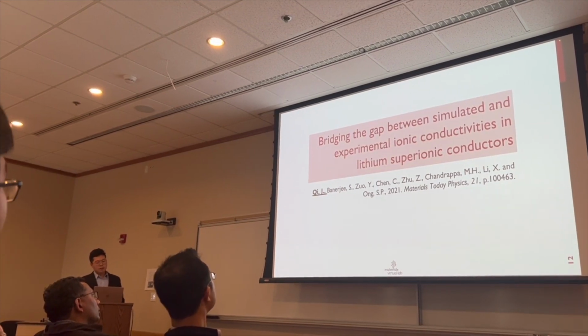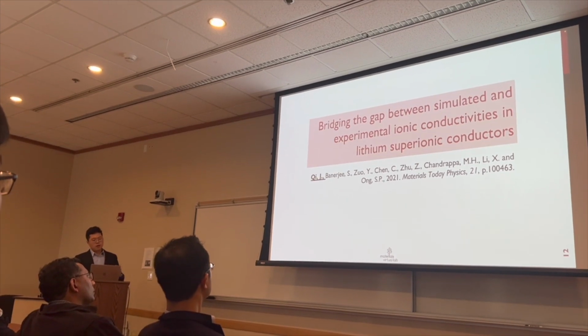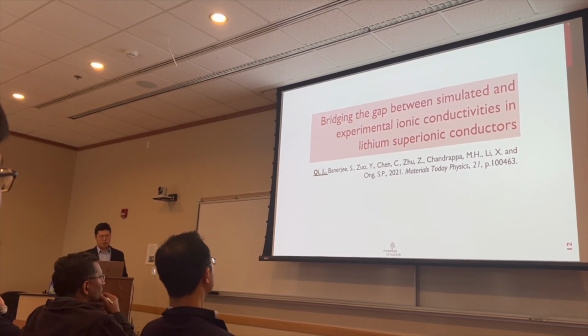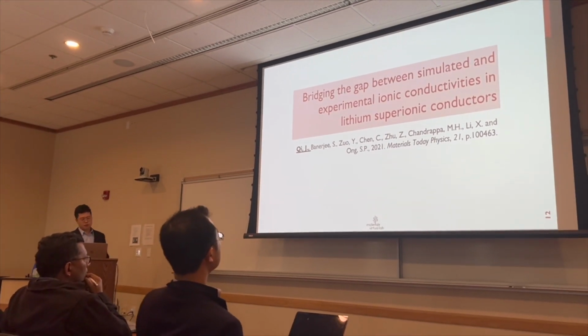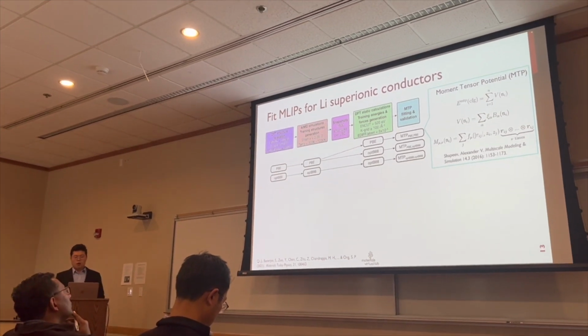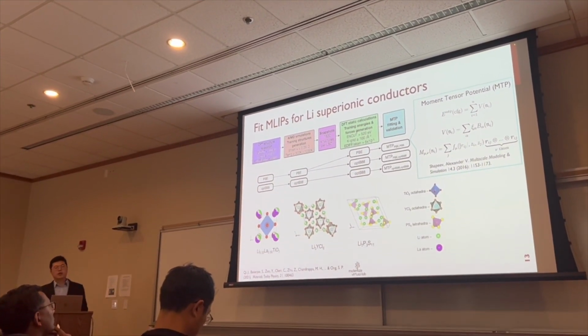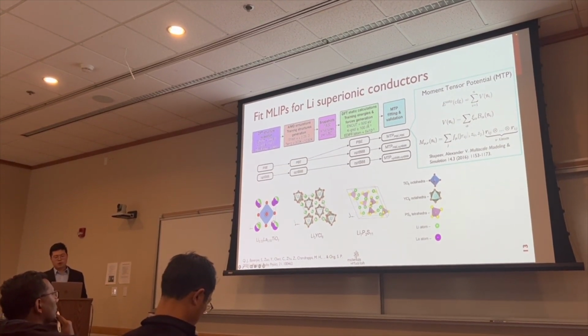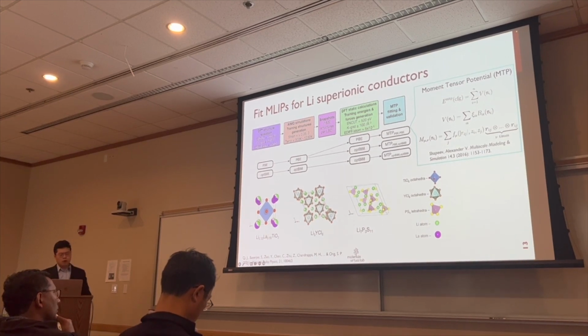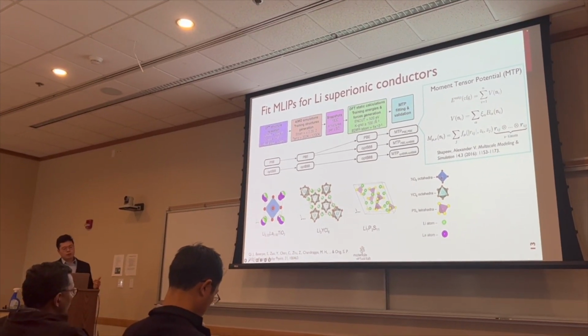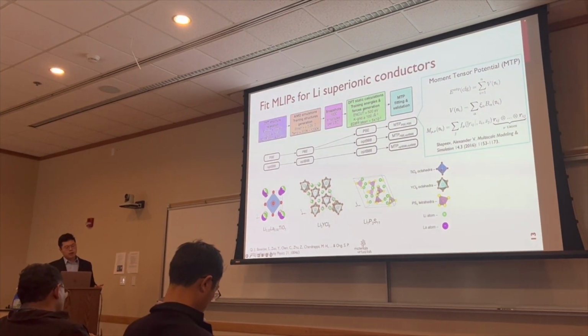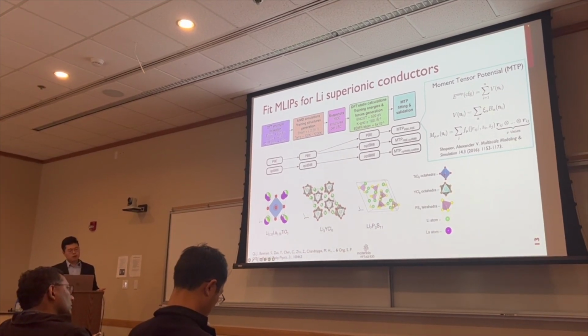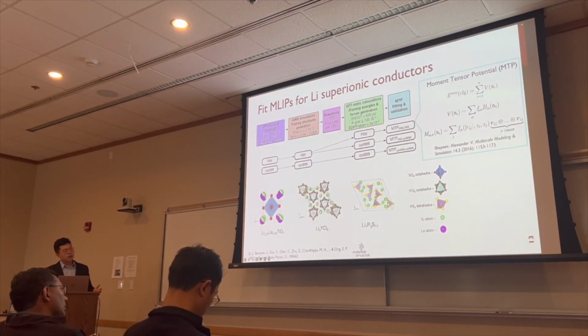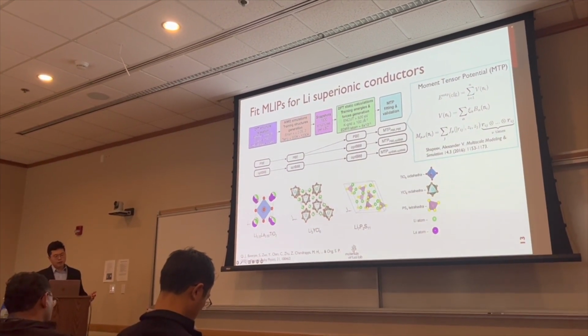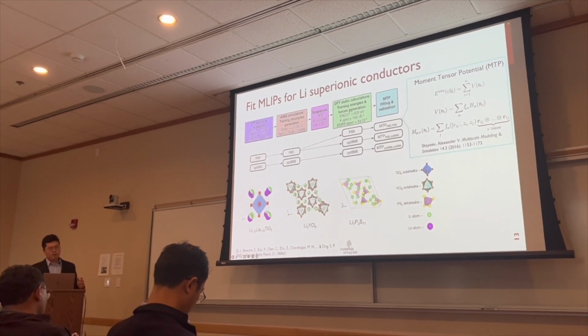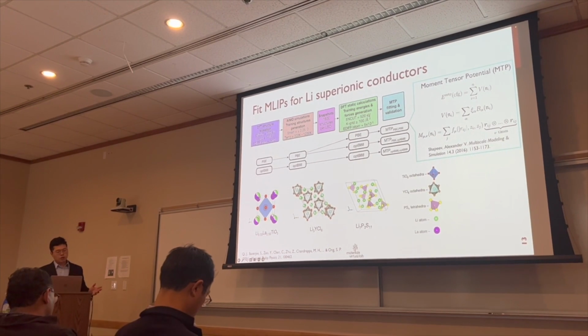topic that I want to discuss for my PhD study, which is bridging the gap between simulated and experimental ionic conductivities in lithium superionic conductors. In this study, we use this workflow to fit moment tensor potentials for these 3 lithium superionic conductor systems. In this workflow, we first perform DFT relaxation to get the ground state structure. Then we perform AIMD simulation to collect 1,800 structures for each lithium superionic conductor. And we conduct DFT static calculations to get accurate energy and forces as training data for different systems. And MTP is fitted with those training structures and data.